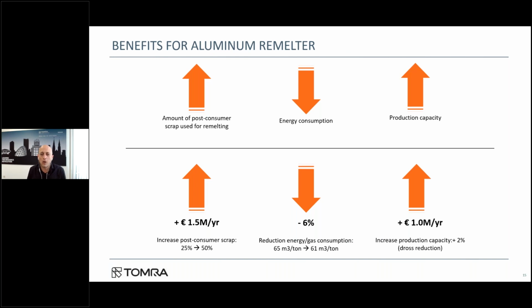So from the perspective of a remelter who uses the sorted post-consumer scrap in their furnace, there are several benefits. First of all, the amount of secondary or post-consumer scrap used in the melt can be increased, or at the very least optimized, when the content of zinc, copper and iron is low and consistently low. I think consistency is the key word here, as it is very important for the remelters to know and to rely on the quality. Of course, when using more scrap, the energy consumption will be reduced. And in addition, when using cleaner scrap, the amount of dross is reduced, which leads to less cleaning of the furnace and increased production capacity or tap-to-tap time.